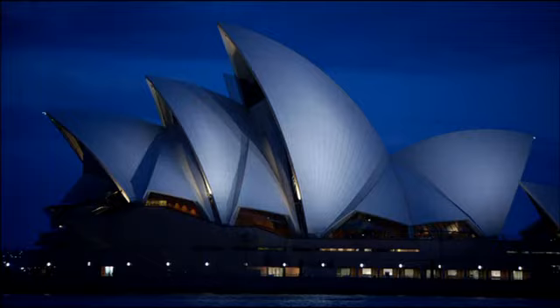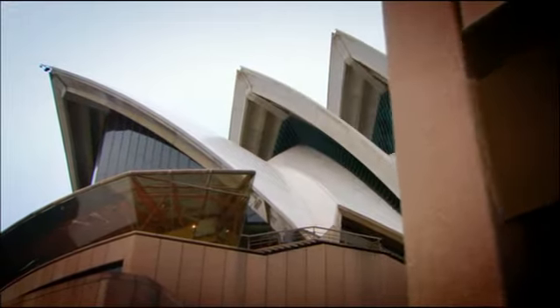So that whole lot will go in how long? In 12 months, that'll all disappear. All eaten away, and that's protecting it all in here. Protecting all the steel inside the heat exchangers. Billions of litres of seawater have passed through the Opera House in 35 years of operation, but its air conditioning system is still uncorroded.